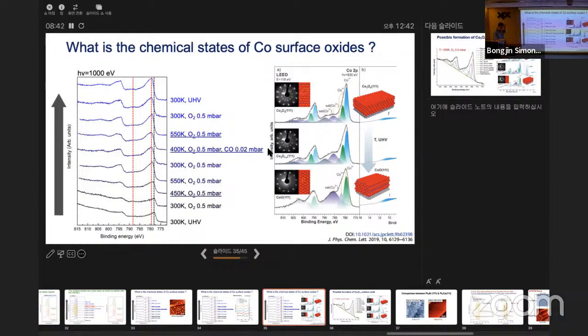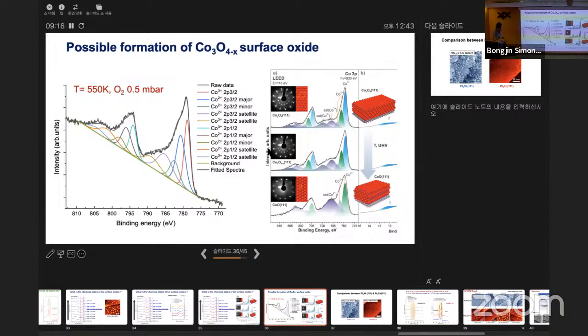It's very difficult to do the peak fitting of the transition metal 2p state, especially. There are many processes involved, but nonetheless, this gave some guideline for the chemical state of the cobalt oxide, Co3O4 and CoO. Based on this, we could estimate that we might have something in between, some mixed state, which is fine. So we tried to fit it, and this fitting can be very challenging. Later on we'll run another experiment. We try to increase the temperature and the photon energy to reduce the background, and we were trying to fit it, and it worked out relatively okay, but we're still scratching our heads about whether that is really the case.